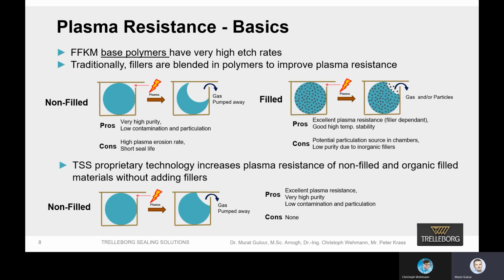But when we talk about filled systems, sometimes those filler particles can become free after the plasma exposure, because they are very much plasma resistant and they can't be etched away. And if they become free, they can cause some particulation in the chamber if an inorganic filler is used. If an organic filler is used, a similar thing to the non-filled example on the left-hand side will also happen. It's not going to leave particles or filler particles released, but all the etched products will be pumped away.